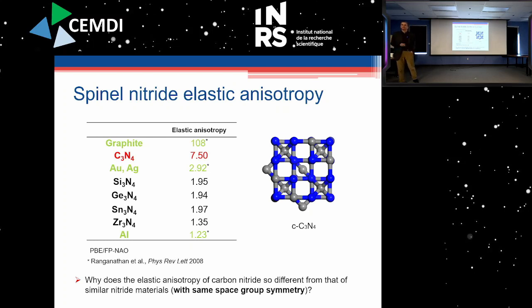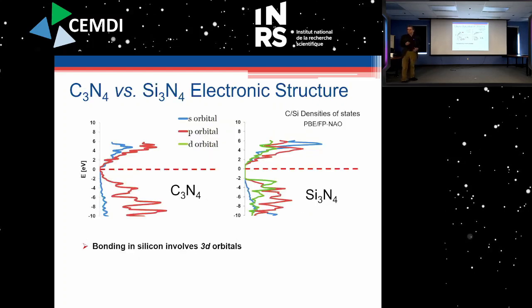So you can expect different mechanical behavior if you have different phases, but within the same space group symmetry, how come we have such a different mechanical property? And so this has to be due somehow to electronic factors, because we have the same space group symmetry, different mechanical properties that must stem from electronic properties. And of course, as chemists, we should have known this all along. What's the big major difference between carbon and silicon and the other group 14 elements is that the d orbitals of silicon are actually much more accessible than those of carbon, if you look at the energy levels of the atomic orbitals.